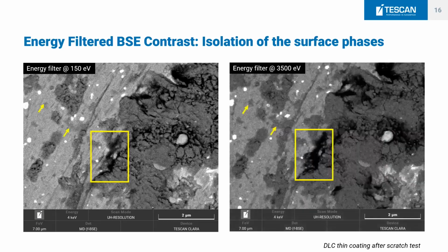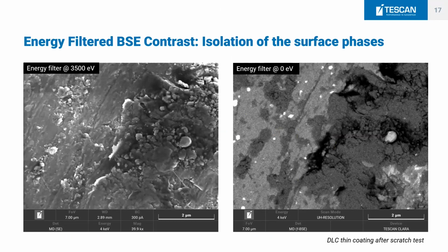But if you apply energy filtering capabilities, you see that some of the features of the material change phases, and they are revealed. So here we just applied energy filtering for incoming backscattered electrons, and you see a change in the phase, and you get very different information. That's what I was talking about before, that at first glance you may have made a bad judgment. So this provided additional information, and you could see that there is way more of the origin layer adhering to the substrate. In this case, it was some iron-based alloy. You could use the secondary electron image on the left-hand side, where you could see all the features, but you can't really tell the materials apart. So you really need the energy filtering to give you an idea about what is what.